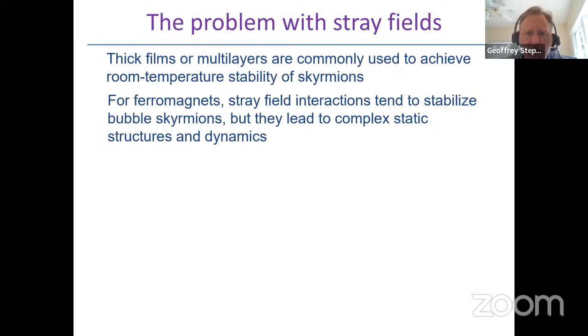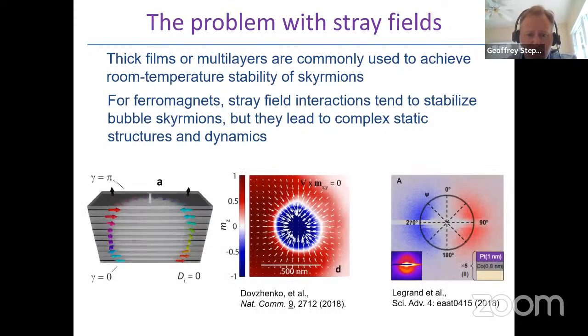They lead not only to larger sizes, but also to very complex static and dynamic behavior of these spin textures. So we now understand that in magnetic multilayers, the stray fields not only stabilize this bubble-like skyrmion as a whole, but also cause interactions from one layer to the next that lead to complicated through-thickness spin textures in these materials. So closure stray fields will lead to, even in the case of zero DMI for a